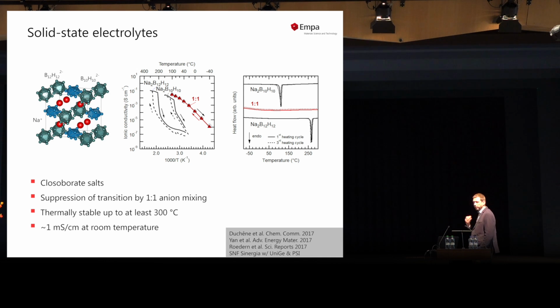It was already known in the literature that when you heat these materials to a higher temperature, they undergo a structural phase transition to a higher symmetry state, which has a higher ionic conductivity, which is in the range which we would expect, which we need for making a battery. You can see that this phase transition also leaves this trace here in the calorimetric measurements, where you can clearly see an endothermic signal.